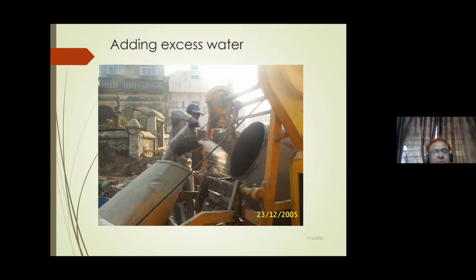So the person who is already casting the slab makes a whistle from the slab, and this whistle is heard by the waterman, and he gives this type of sign for the water. He will add excess water on the side, and our mix design of 0.35, 0.45 will go to 0.5, 0.6, and 0.7 water cement ratio by this gesture. So our concrete will be ruined and our mix design will be vanished.